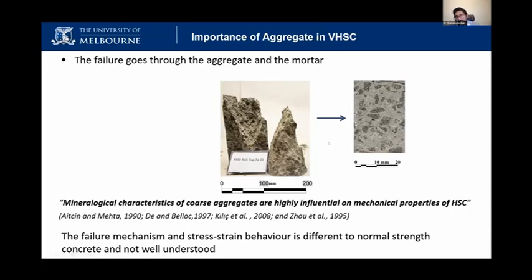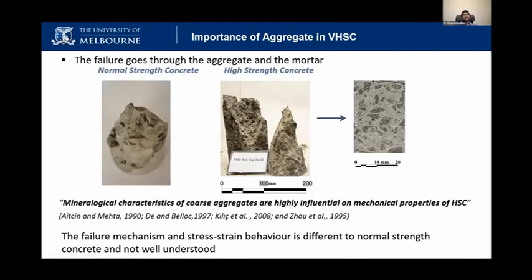From our studies, what we found is that it's very important to have the proper aggregate. This is the failure of a normal strength aggregate. You can clearly see the aggregates are not broken. The failure has gone around the aggregate. That's the big difference in the failure pattern.